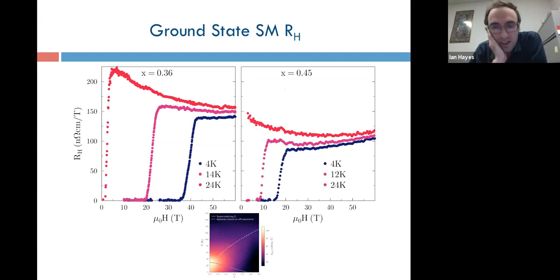Let me start by showing you what the data looks like at low temperatures. These are slightly overdoped samples, 36 and 45% phosphorus doping, so they live around here. You can see a strong decrease in RH at moderate temperatures of 25 Kelvin or so, and then that decrease definitely weakens as you go to lower temperatures. At higher fields, you can see that the increasing RH is setting in again, and in between there's sort of a balance between the two. It's a little bit stronger for the 36%, whereas at 50 Kelvin, you're already moving into the H squared regime for the 45% doped. In each case, there is still a bit of decrease that you can observe.